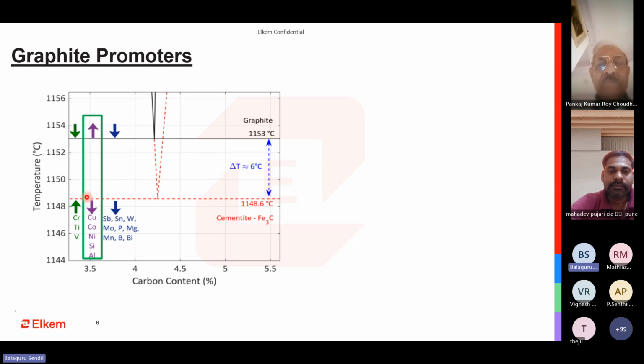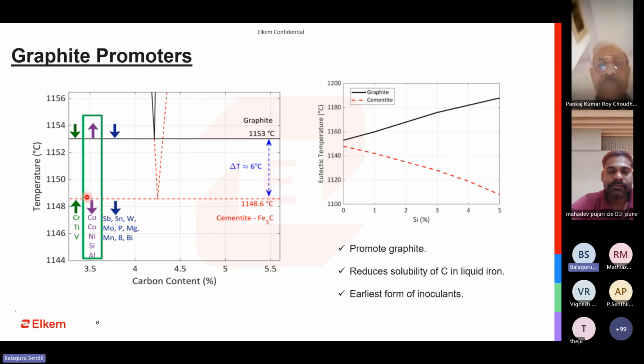So these are some of the elements which can actually be graphitizing elements. The most common one I would like to address here is silicon. What does silicon do? It promotes graphite, and silicon is some of the earliest form of inoculant. The plain ferrosilicon is still being used, and it is a very capable inoculant depending upon the foundry condition. If a foundry has compromised on its methoding and gating and casting yield is not an area of concern for that foundry, then we can work with a very plain ferrosilicon based inoculant itself.